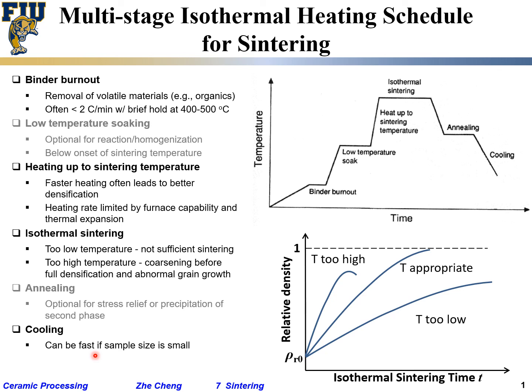But if the sample is very, very large, quite often be very careful when you cool, because thermal shrinkage may cause cracking in sharp corners, locations like that, so-called stress concentration locations. Make sense? Because the inside and outside, if you cool too fast, the outside may go very quickly to low temperature, inside is still hot, and that creates a lot of trouble, micro cracks. Okay? Thermal stress and sometimes for precipitation, for phase change. Okay?